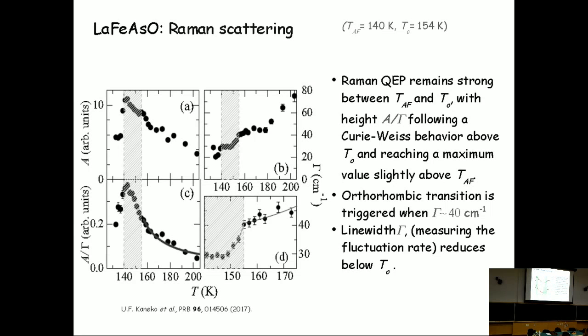And you see that both the area and the height keep going up. The first temperature, at 155, is the orthorhombic transition temperature, and the second one is the magnetic transition temperature. And in green, you have the nematic phase. You see that the signal keeps going up in the nematic phase up to temperatures which are very close to the magnetic ordering temperature, which is surprising in a sense, because it has always been accepted that the nematic transition temperature coincides with the orthorhombic phase transition, not necessarily with the magnetic phase transition. At least for this sample, we are seeing critical fluctuations that keep going up after the transition, which was thought to be the critical temperature for these fluctuations.